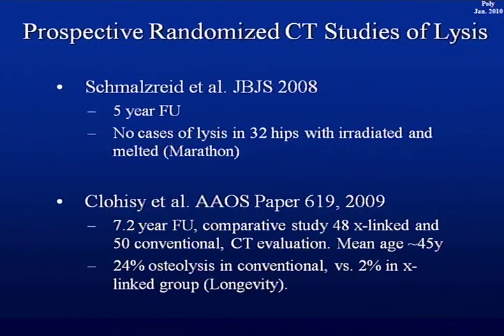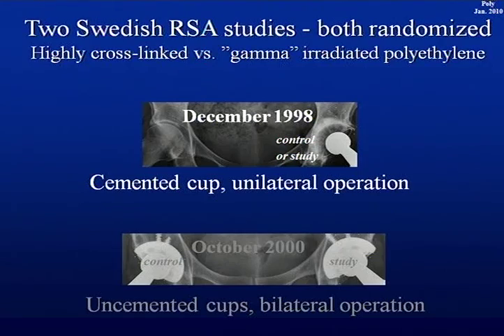There have been 2 studies published, one from Schmalzreid, 5-year follow-up on Marathon, and he couldn't identify any cases of lysis in 32 hips with irradiated and melted. And Clohisy and Maloney, a paper that is coming out now, presented still as a podium, had 7.2-year follow-up in a comparative study of highly cross-linked and conventional using CT as evaluation, with a young mean age of 45 years, very active patients. They had 24% osteolysis in the conventional. There was one case that maybe had osteolysis in the Longevity group, more or less confirming what we are finding.